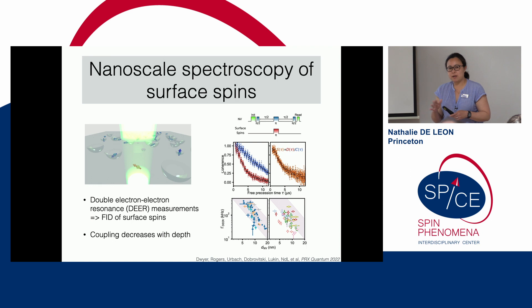As a spoiler alert, we have not looked at any condensed matter targets yet, so this is a very NV-centric talk. One system we've studied for a long time is parasitic contaminant surface spins at the surface of diamond — they're always there and you can't get rid of them. We see these spin defects at the surface that are g=2, spin-1/2, and excess noise near the surface as you bring NV centers very close to the surface.